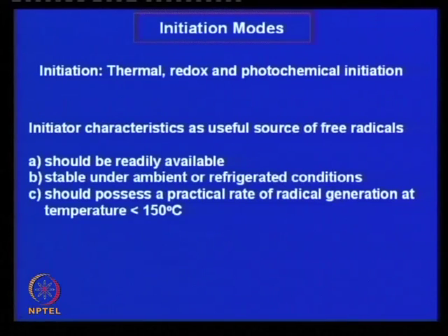So, in order to avoid all those problems, it is better to polymerize at lower temperature, which can be controlled, so that the entire polymerization kinetics remains under your control. Although polymerizations are carried out at higher temperature for some cases, say gas phase olefinic polymerization, such as polymerization of ethylene, propylene, etc. If you look into the literature, you will find the technology of manufacture of polyethylene and polypropylene uses high temperature gas phase polymerization.